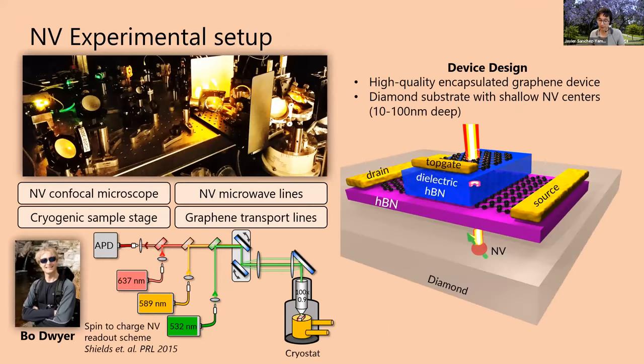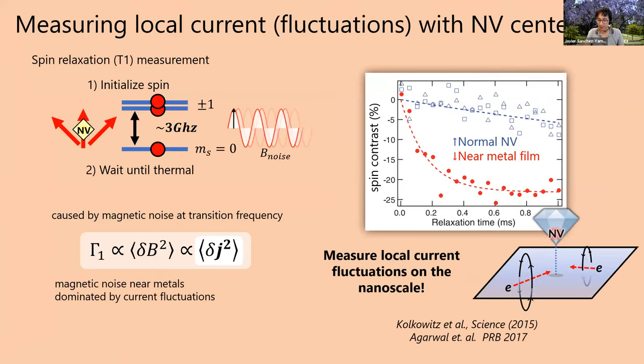Here's a quick picture of our NV setup. It's a cryogenic NV setup. It's a confocal microscope, microwave lines, graphene transport lines. We implemented a kind of nice way to read out the NV center efficiently at low temperature that people had not done before, using resonant readout. And again, this is our sample, which is a graphene device on top of a diamond substrate with NV centers inside of it. All right, and again, we're doing a relaxation measurement, which is gonna probe the current fluctuations in the graphene.